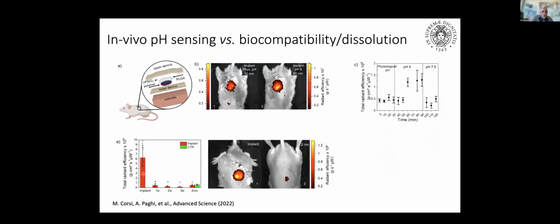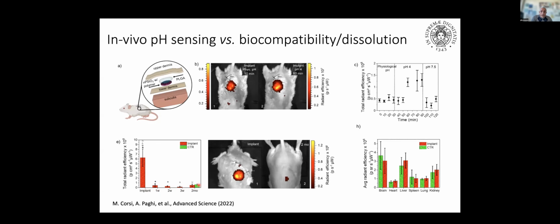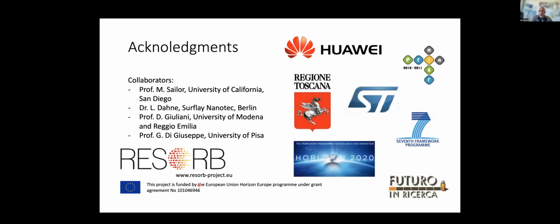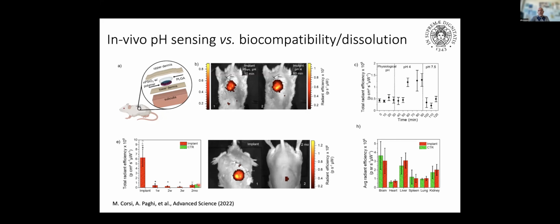We double checked also the biodegradation in vivo. For example, you see the sensor is still there in the first day, but after 1 week, we don't see the sensor anymore. And then after 2 months, we haven't found any residual of the sensor. And then after 2 months, we did organ explantation. We double checked any possible biocompatibility issues in the different organs, from brain to kidney, and also in the skin, and we haven't found any trouble with that. So basically, this was our first work on bioresorbable chemical sensor.